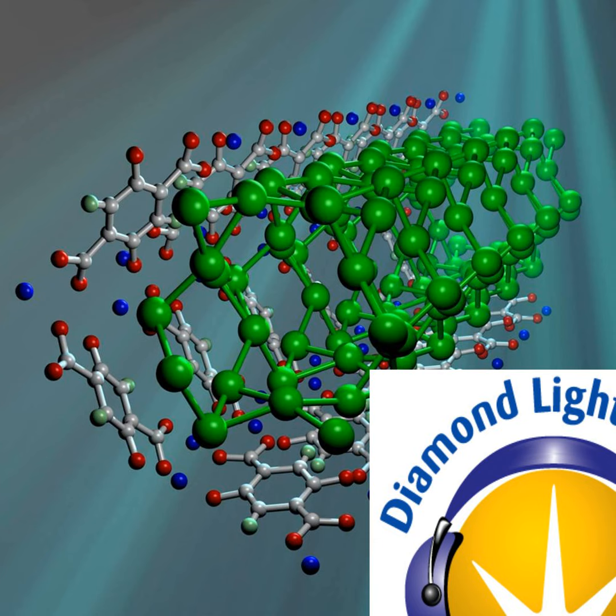And the material has very excellent properties in the selective capture of CO2 and SO2, while all the other common small molecule gases, such as hydrogen, oxygen, nitrogen, carbon monoxide, can pass through the material with very little uptake. Actually, the uptake would be 100 times lower than that of CO2 and SO2. In this way, this material is able to selectively grab the CO2 and SO2 from a cocktail-like gas mixture.